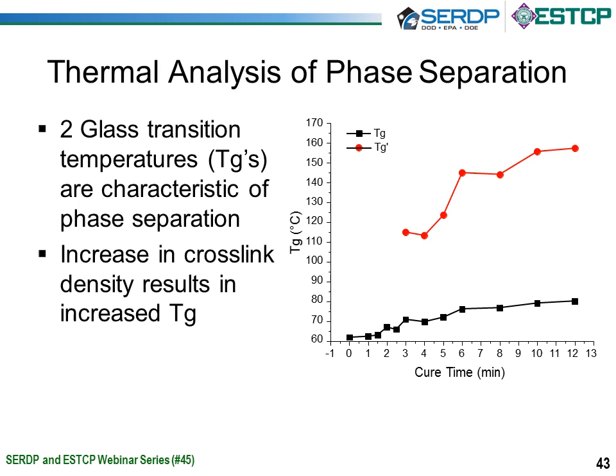It was specifically DSC. We can see on the right side that we start off the polymer with a glass transition of approximately 60, and this is very consistent with commercial powder coatings in that a relatively low glass transition is required to ensure thermal stability on storage.